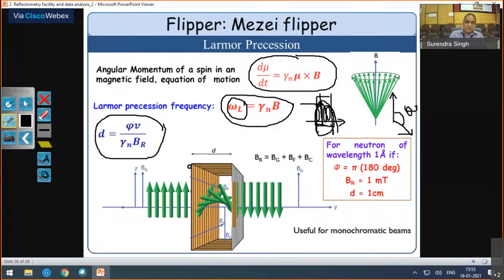Then you have a flipper over here, which is a magnetic field you are applying perpendicular to the neutron spin; it is shown going into this plane. So this is Bf, which is perpendicular to the spin of the neutron. You apply uniform Bf along this distance d. And because Bg is already in this direction, to cancel out that Bg you have to apply Bc also, because you just want Bf, the perpendicular field, and no other field in this d direction, a uniform field. So that's why it is written here.